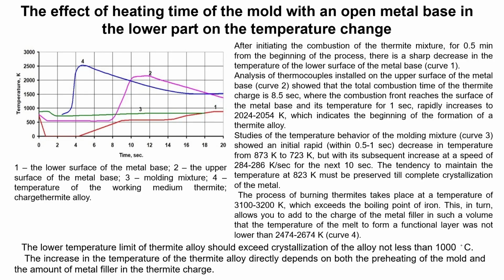After initiating the combustion of the thermite charge, 0.5 minutes from the beginning of the process, there is a sharp decrease in the temperature of the lower surface of the metal base. Analysis of thermocouples installed on the upper surface of the metal base, curve 2, showed that the total combustion time of the thermite charge is 8.5 seconds, when the combustion reaches the surface of the metal base and the temperature within 1 second rapidly increases to 2054 kelvins, which indicates the beginning of the thermite alloy formation.